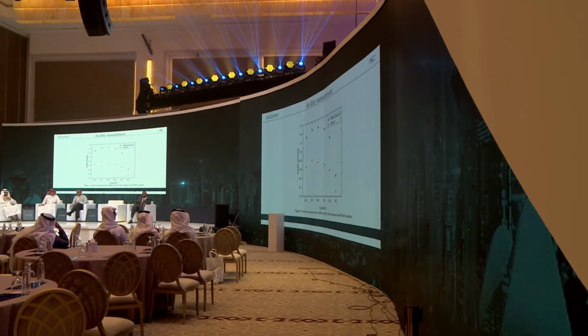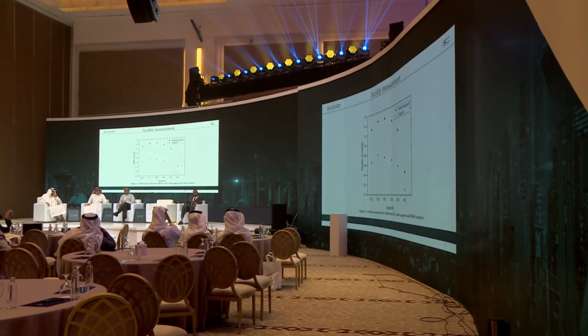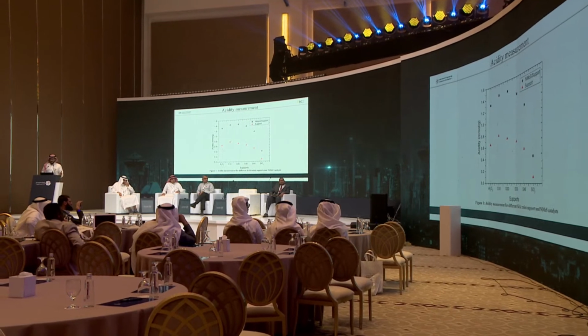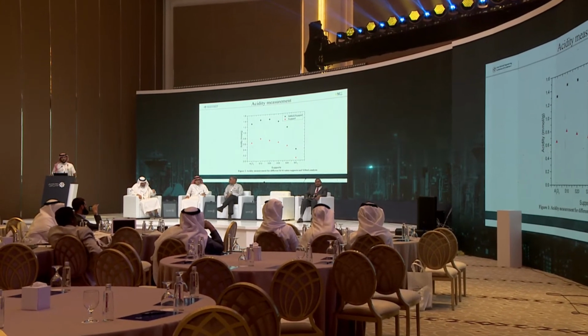Here we want to talk about the acidity measurement that we said we use ammonia TPD for. Here there is an acidity change because of the support composition. We said that the support composition goes from 100 silica to 100 alumina to 0 silica, and also because of the addition of NiMo, which is the addition of the nickel molybdenum sulfide catalyst.